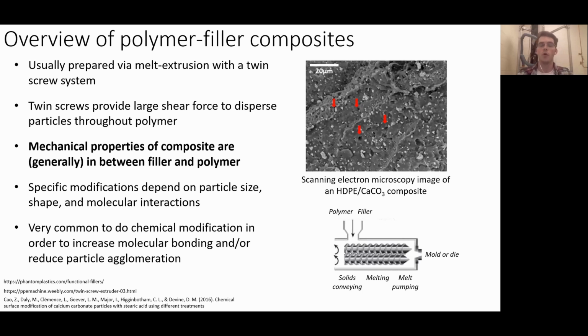But overall, the mechanical properties of your composite are generally in between that of your filler mechanical properties and your polymer mechanical properties. This is an intuitive application of the rule of mixtures, which I'll also discuss in the next couple of slides. So you can make specific modifications to your polymer based on the particle size, the particle shape, and the chemical composition of your particle, which plays a role in the molecular interactions with the polymer. So it's very common to modify the surface of your particles with some sort of chemical in order to increase this bonding and or reduce particle agglomeration, which is also important for mechanical properties, as I'll discuss later.